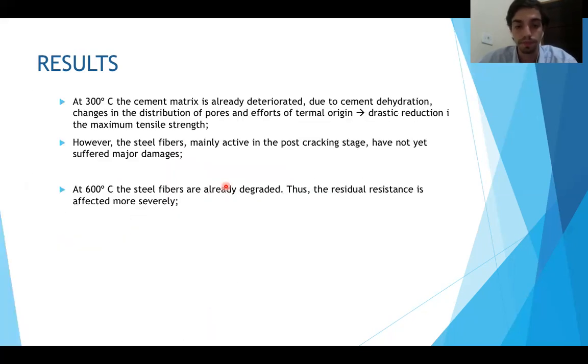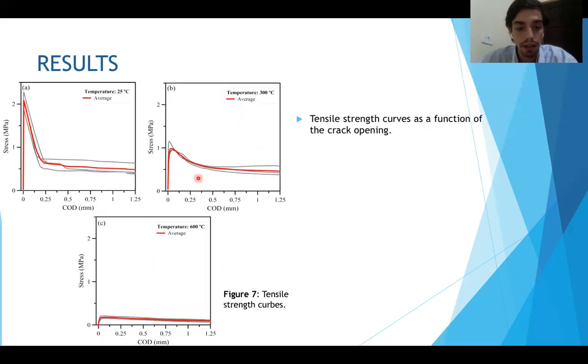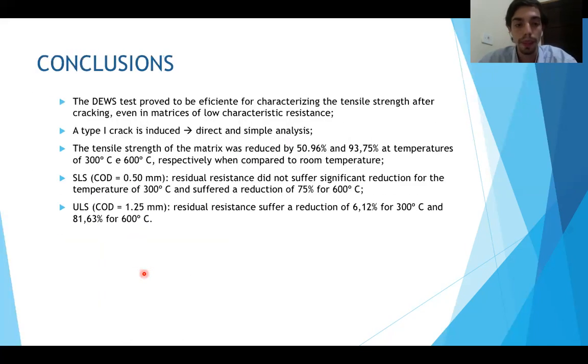At 600 Celsius degrees, the paste deteriorates further, reducing the peak resistance, and it's noted that there is practically no peak. In addition, the steel is already deteriorated. Therefore, the fibers that have the role of sewing the matrix do not sew as well, reducing the post-cracking strength. What you observe then is that the fibers fulfill their role after rupture, ductilizing the structure and preventing a fragile collapse, increasing the safety margin for temperatures of up to 300 Celsius degrees.